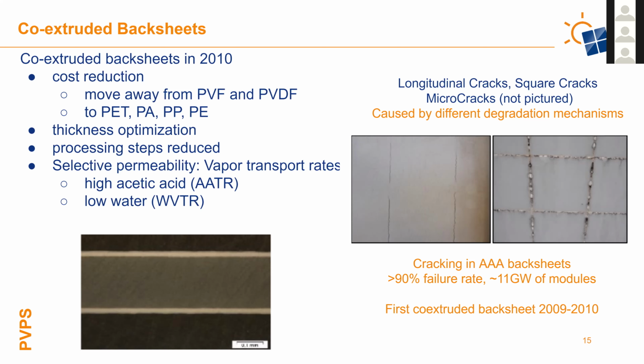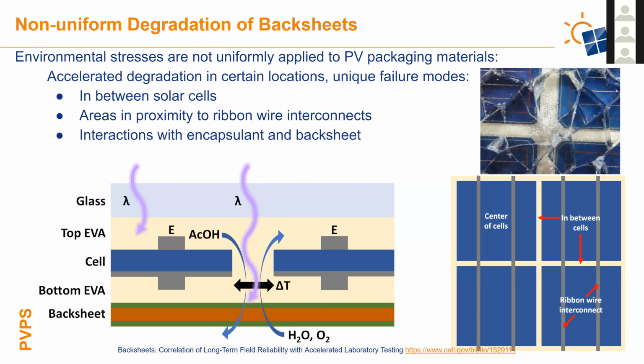This has been found in other cases as well. Here's a picture where the glass is shattered in this module from us cutting it up, but you can see these cracks between the cells. This is a polyamide backsheet, and what's happening is there's higher irradiance there, a difference of temperature, and acetic acid forming in the EVA, which potentially attacks the polyamide and starts degradation between the cells.